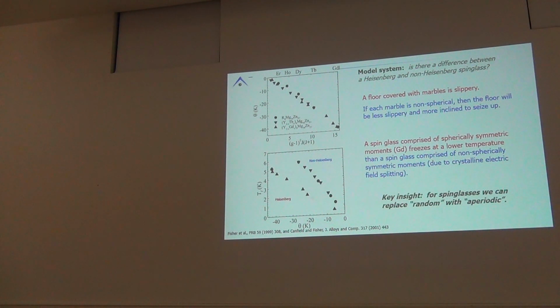Very well understood. On the other hand, if I look at the freezing temperature versus theta, two measured parameters, this is my high temperature Curie-Weiss theta, this is the temperature at which it freezes at low temperatures, it breaks into two manifolds. I have one manifold for my Heisenberg, pure gadolinium, and this yttrium-gadolinium substitution series, and another one for my non-Heisenberg, all my other rare earths, and the yttrium-terbium dilution series. There is a clear difference, okay? Basically, the non-Heisenberg, the anisotropic moments freeze up at a significantly higher temperature.